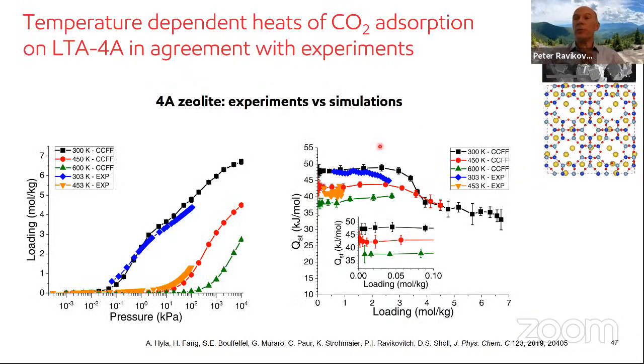When we saw this, we were very much surprised. So this is the 4A zeolite, and this is CO2 adsorption on 4A zeolite. On the left, you see experimentally measured isotherms and simulated isotherms. There is a very good agreement. Not perfect like for siliceous zeolites, but not bad at all, really good. And on the right, you see simulations of the heat of adsorption and experiments. So simulations at 3 temperatures, experiments at 2 temperatures.